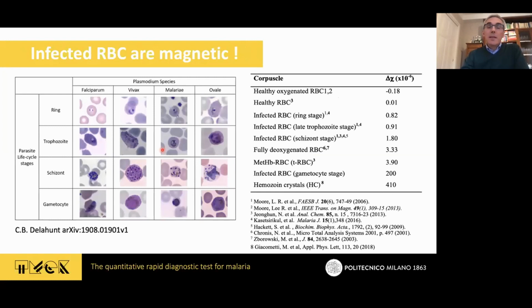Now, what is the entity of the magnetism? It is just a tiny susceptibility, a very, very small value. Here you see in this big picture the evolution from the ring to the trophozoite, schizont, and finally gametocyte stage for different species: falciparum, vivax, malariae, and ovale. And you see that there is an increase of the volume occupied by the hemozoin. And in the gametocytes, half of the volume is occupied by hemozoin nanocrystals.